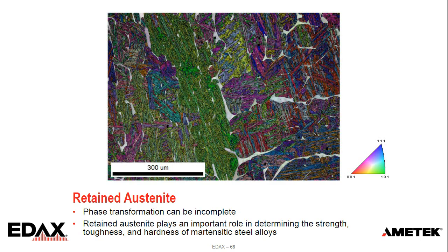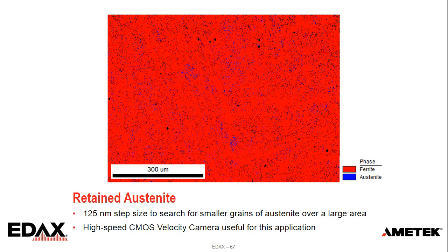That comes back to this: as we do this transformation, you can also have retained austenite, where not all the austenite has transformed. Retained austenite can be an important factor in determining the strength, toughness, and hardness of some alloys. As we go to look for this, I've sometimes called it a needle in the haystack problem. We want to look at a large area, but with a fine step size. That's where some of these faster, high-velocity CMOS type cameras are really useful. We can look at larger areas with finer step sizes. That's what we're showing here, doing 125 nanometer steps, looking at the ferrite and austenite. The blue are the smaller regions of austenite that are present.